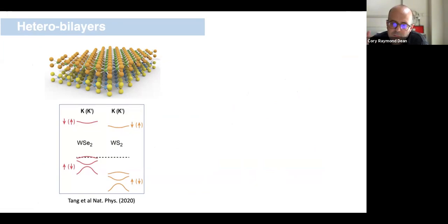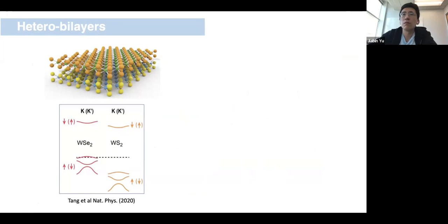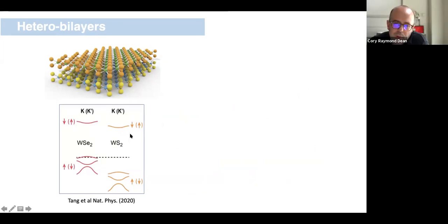Let me just finally say that in addition to homobilayers, we can study heterobilayers. In the most broad view, one of the interesting features of the heterobilayer is that we simplify the system even further. Here's a rough cartoon picture of the band alignment for a heterobilayer. In this case, for WSe2 and WS2, the band alignment is such that one of the layers is pushed to a much lower energy than the other.